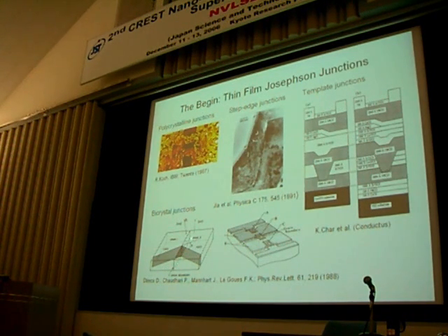This was then quickly cultivated in these bicrystal junctions, where you have two crystals with a different orientation. You deposit the film on top and thus get a very nice linear grain boundary, and if you make some structures on top, you find that this behaves like Josephson junctions. They are still around and they are dominating the SQUID market, the superconducting quantum interference device and sensor market.